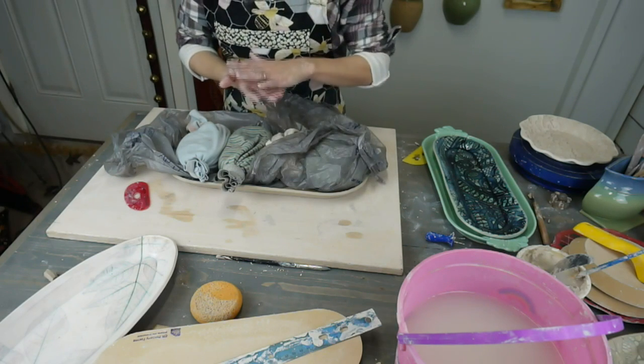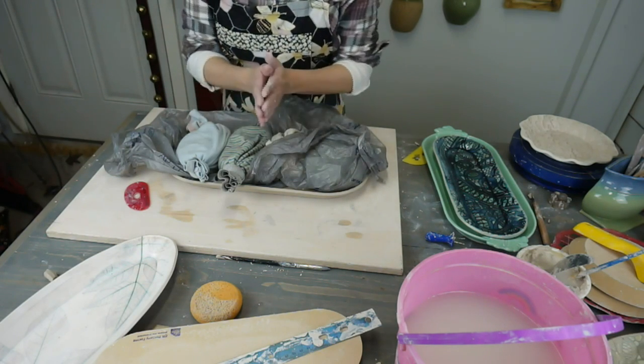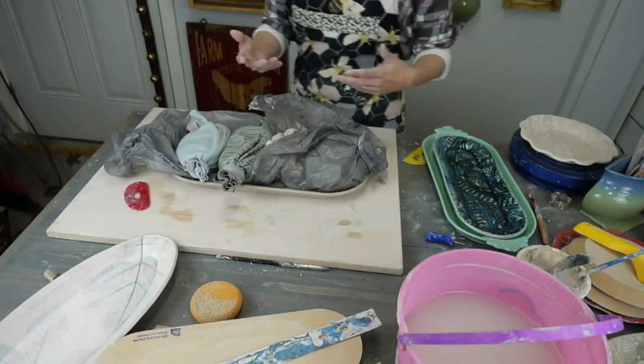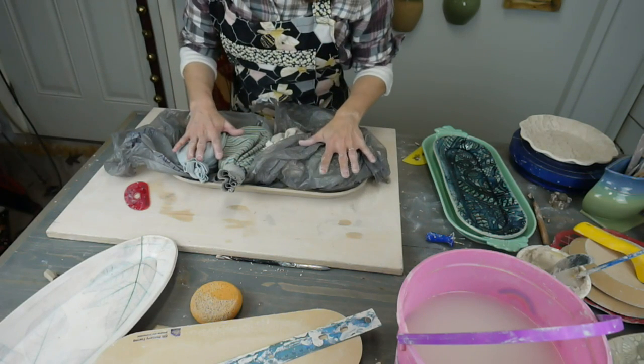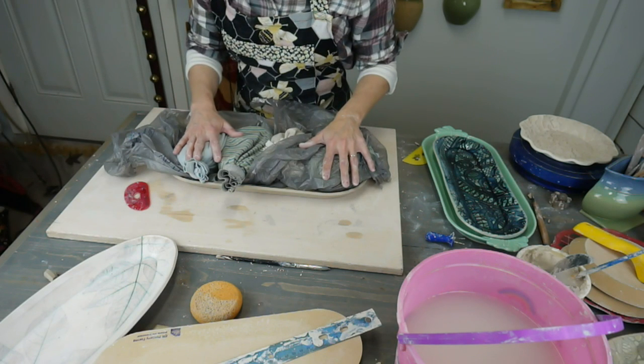If it's a large area, you need to put something under it in the kiln. I use alumina hydrate under it — that helps it move. Also, you have to have a shelf that's completely flat. So after this is completely bone dry I will leave it with weight bags until it's 100% dry.